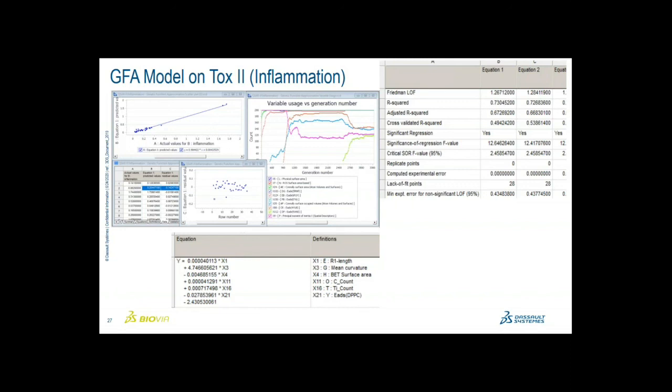The GFA lets you choose or limit the number of terms in your equation. So here we see that the most relevant for our response is the length and the shape and the surface area. So all the volumetric, of course, as was mentioned before by Otmar, I believe, is extremely important in the response, but also the nature here, carbon or titanium nanoparticles. And then the adsorption of the DPPC, again, you see arrives. So the interaction with lipids, as computed, seems to be a very important factor.